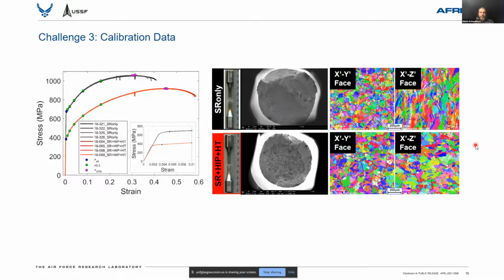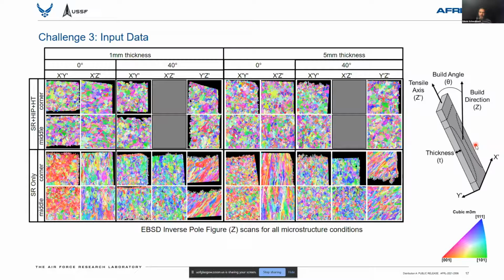We provided very similar, essentially the same descriptions of the microstructure, but now we're looking at a very broad range of specimen geometries. So we are varying specimen thickness in the as-printed configuration. We're varying the orientation of these objects. In some cases, we have as-printed surfaces. In other cases, we've removed both the roughness and the near-surface microstructure from the specimens. And then we're also exploring a couple of different heat treatments in these materials. So again, the microstructure descriptors were provided, and the request was to predict various aspects of the stress-strain behavior.